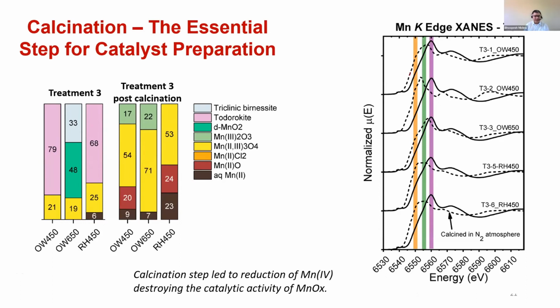So what we saw is that when we calcine, the calcined material is in dotted lines and the non-calcined material is in solid lines. So you consistently see that the calcined material, and of course this line represents manganese 2, the green represents manganese 3, and this magenta represents manganese 4, there's a reduction of manganese during the calcination step. So instead of getting much better and well-formed catalysts, we actually went the other way around.